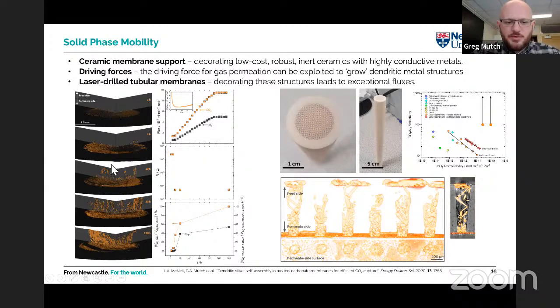And what we were able to do is grow these structures, these silver structures, versus time inside the membrane. And once those silver structures span between the feed and permeate side, you see that the electrical conductivity or the resistivity changes significantly, about 3 orders of magnitude difference. So no conductivity in this system, very, very good electron conductivity in this system. But we've been able to do this using a vanishingly small amount of silver.